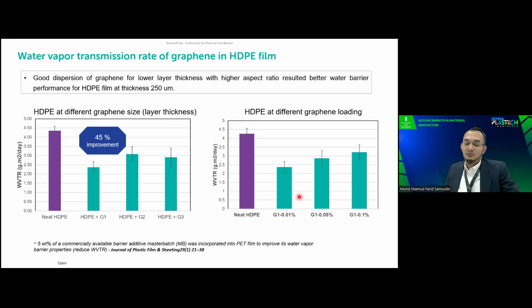So we believe that when we further increase the amount of graphene, it will create agglomeration, and from there it will disrupt the laminar structure of the graphene in the film or in the polymer. And what we can highlight here in terms of the loading of graphene that we use is very, very small. For this case, it's only 0.01.